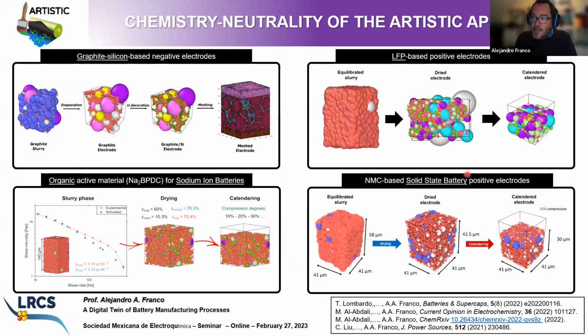And also, we have demonstrated the transferability of the approach for the simulation of the manufacturing process of NMC-based positive electrodes for solid-state batteries. The difference with the three previous cases, in the case of solid-state batteries, is that you need to account for the solid electrolyte particles in the simulation pipeline, right? To simulate the slurry, the drying, and the calendering, right? Therefore, you have more parameters to fine-tune here in the force field approach, but we have demonstrated that the approach can apply and get relevant results.